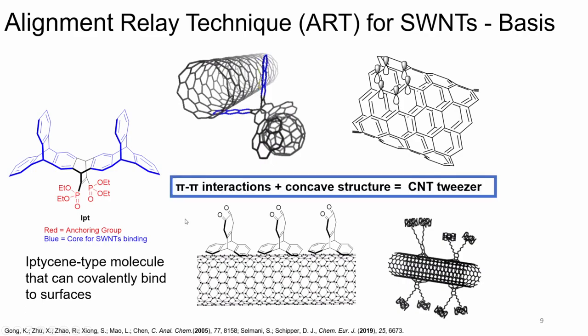So this is really nice that we have this kind of tweezer based on pi-pi stacking, positive pi-pi interactions, and the concave structure, the concave nature of it, which is kind of where the organic synthesis part comes in, designing this molecule for this particular purpose of creating a carbon nanotube tweezer.